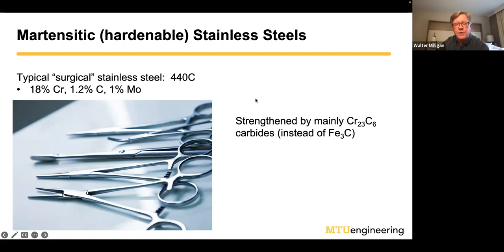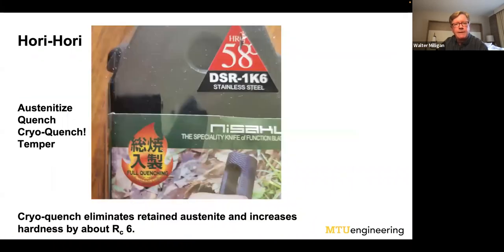And we do the same processes to this. We austenitize it, we quench it and temper it. It's strengthened by basically Cr23C6. It's not just chrome, but it mainly is. And so we can get very high performance by doing that. So once again, there's the hori, and we got 58 Rockwell C, they claim on the label there.